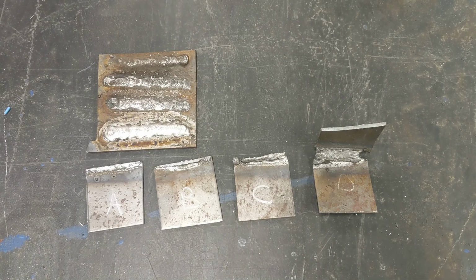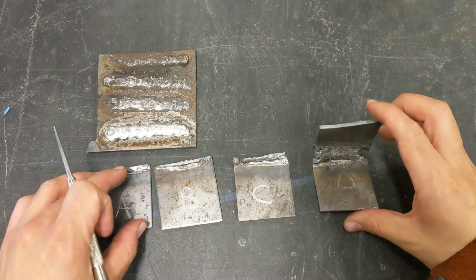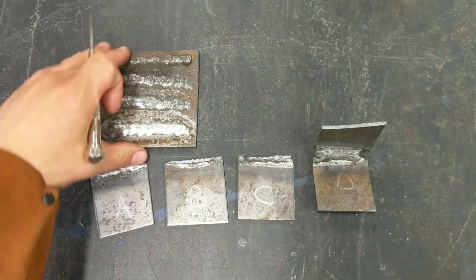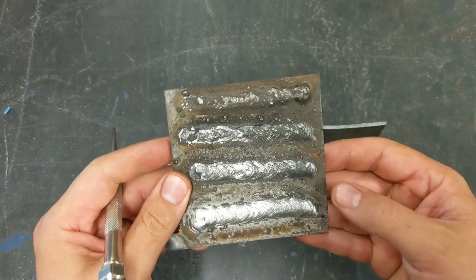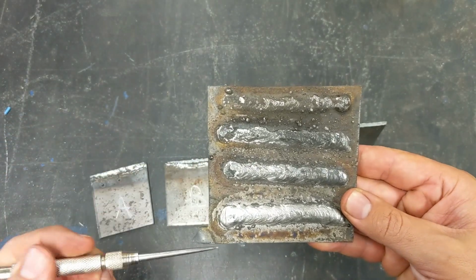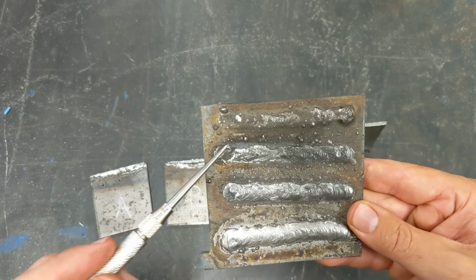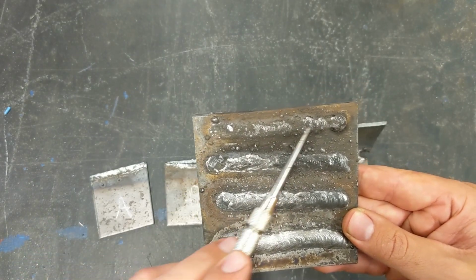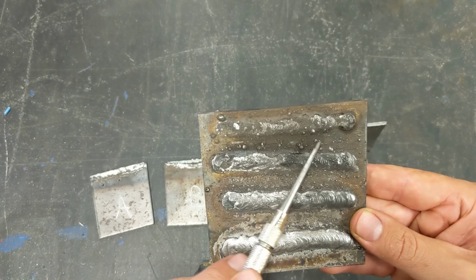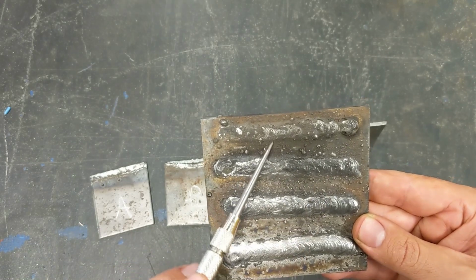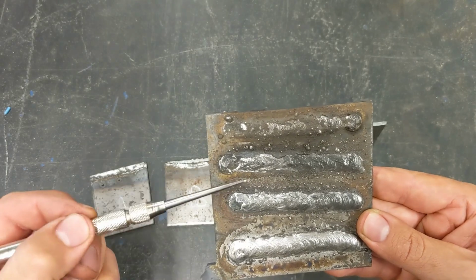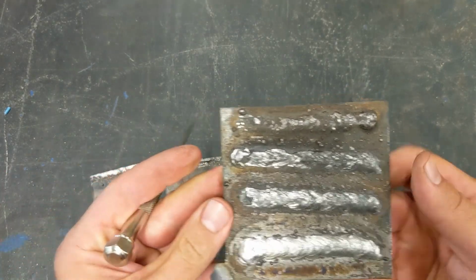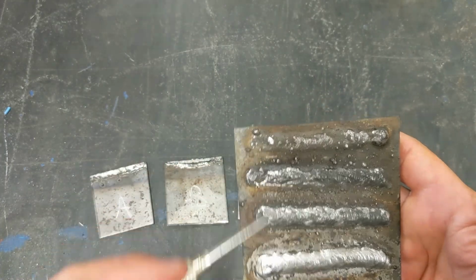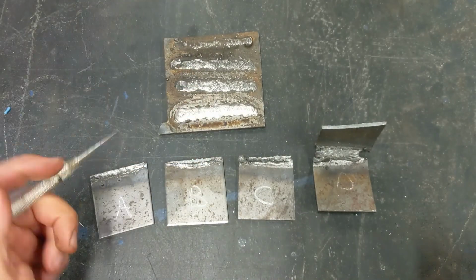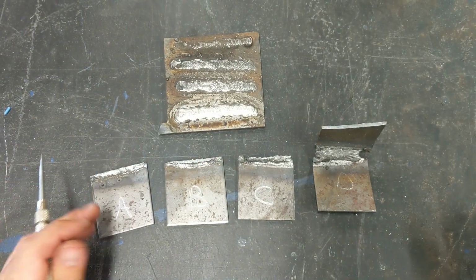Okay, I thought I'd go through here with our final products and just take a look at them. First of all, I wanted to look at our sample plate with our 4 different fluxes and just give you a little bit better picture of what it looks like. Again, the 6011 up here, a very aggressive rod, lots of spatter, a relatively low deep penetrating weld pool, and then all the way down here to the 7000 series where you start to see very aesthetically pleasing welds, all dependent on the flux. So the flux coating of those shielded metal electrodes is extremely important.